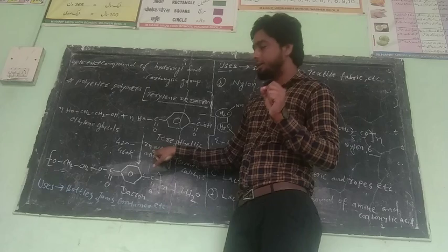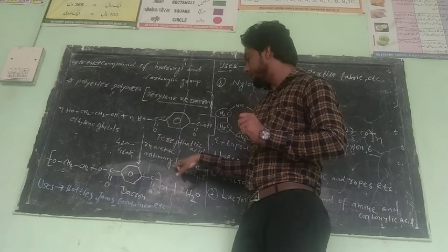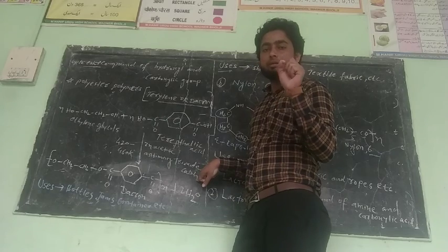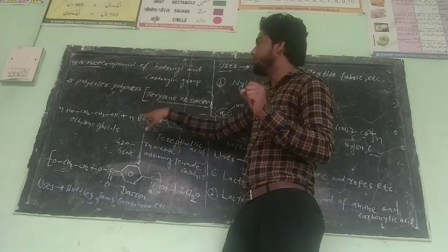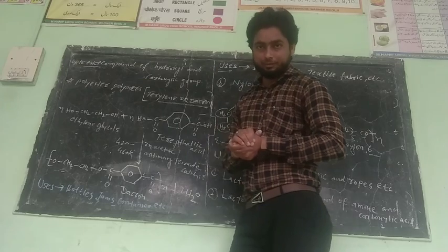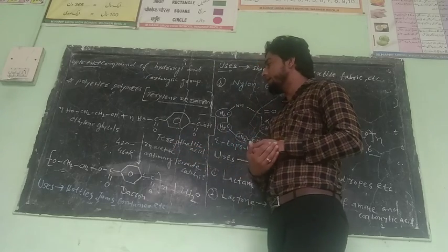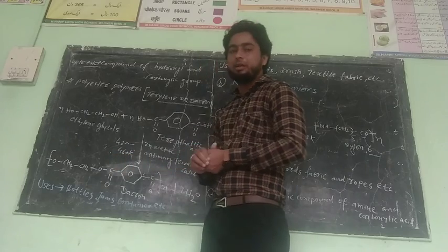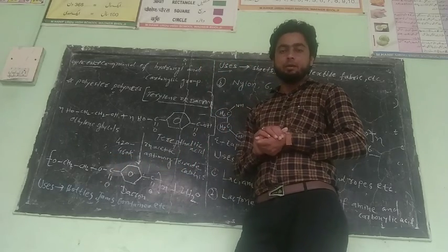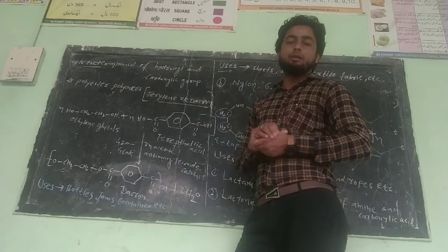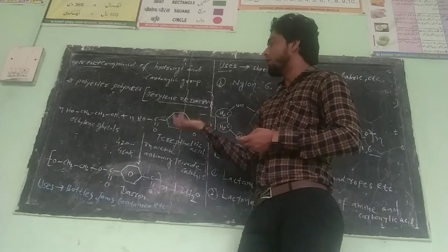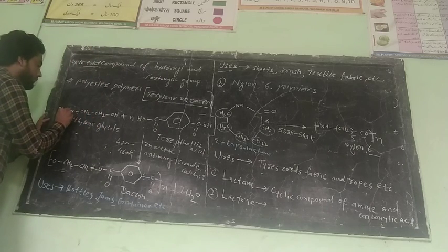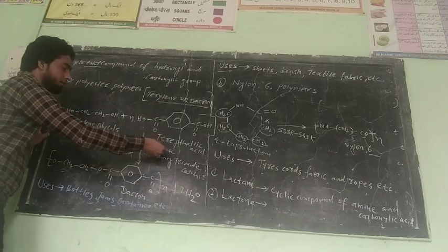Zn indicates zinc acetate antimony trioxide catalyst. In the presence of this special catalyst, polyester polymer is formed. Clear? And this reaction is heated at 420 to 460 Kelvin, a higher temperature, to form polyester, Dacron or terylene. So now, how does the reaction happen? Here the ethylene glycol OH CH2CH2OH reacts with the terephthalic acid.